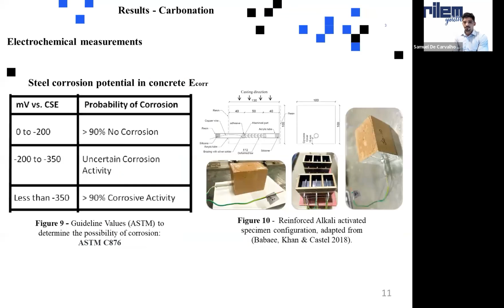So to confirm that, you did some electrochemical tests based on electrical resistivity and steel corrosion potential in concrete, based on ASTM 876. On your right is the sample that you used to perform this test. As you guys can see, there is a reinforcement bar inside of the alkali-activated specimen, and you used a similar specimen to the one Dr. Babaee, Khan and Castel used in 2018 in their paper.